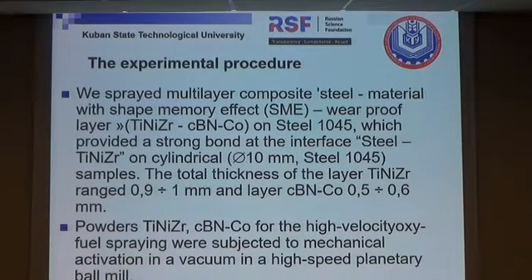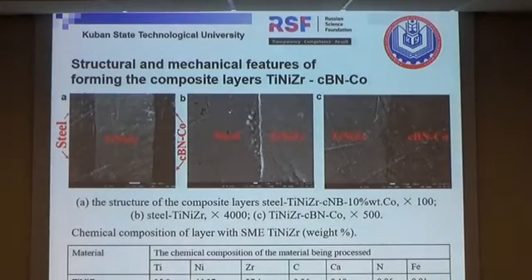was 1.5 mm. Powders of titanium nickel zirconium and cubic boron nitride with cobalt for the high velocity oxyfuel spraying were subjected to mechanical activation in a vacuum in a high-speed planetary ball mill. Structures and mechanical features of the formation of the composite were presented here.